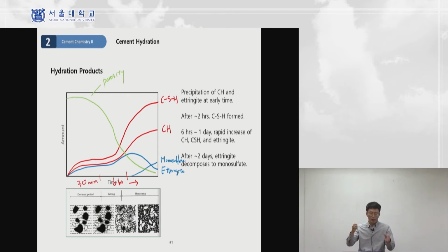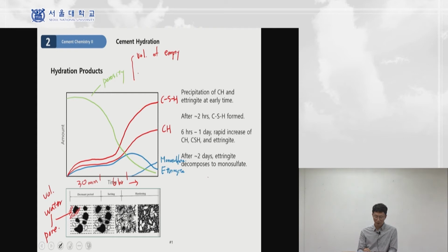So basically, the cement hydration process is the water consumption process. We have a designated volume, and there's a chemical reaction going on, and then all the liquid phases will transform into the solid, right? So basically, there is a reduction of the pore. Pore means a void, and at the beginning, we call the volume of the liquid water, volume of the water, a pore. Okay? So technically, the porosity is the volume of empty region as well as the volume filled with water. So volume of empty and volume of water. And because the chemical reaction of the OPC is a water consumption process, the porosity should decrease as hydration progresses.